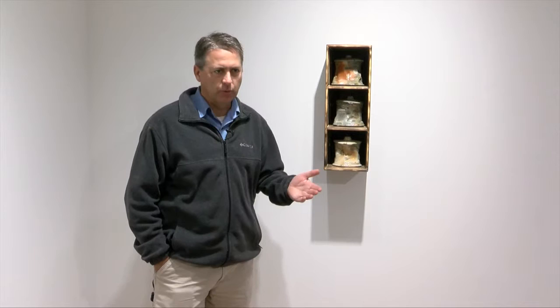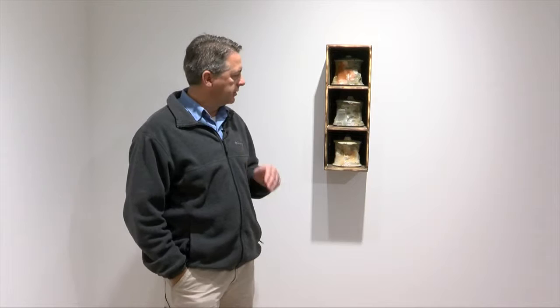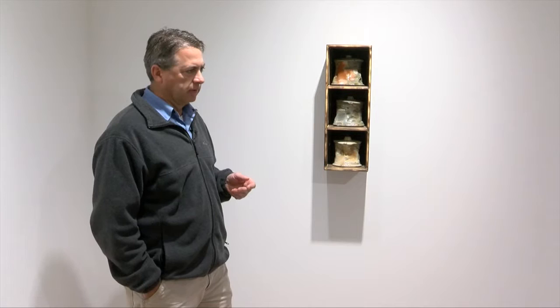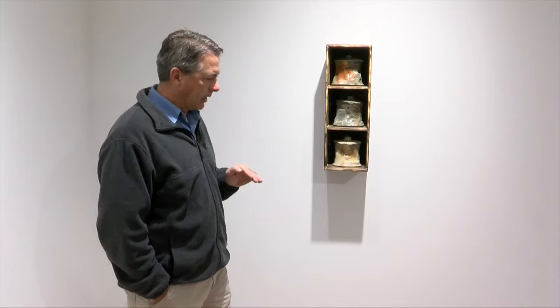The train kiln will hold at temperature for about 14 hours at 2400 degrees to really lay that glaze surface on there. And the Anagama will hold it there for something like 36 hours. So depending on what's going on with the kiln, we do a lot of things, but we're there around the clock, and we have to maintain what's going on, paying attention to specific things, because if nobody's there, it goes out, and then we have a very serious problem.